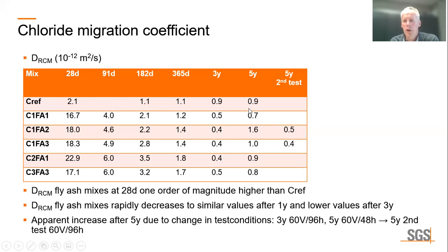Then, after 5 years, the migration coefficients for the reference concrete remains constant, whereas that of the fly ash mixes seems to increase. However, we believe that this increase is an artifact caused by a change in test conditions.